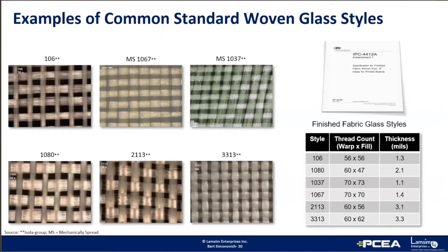MS glass, like 1067 and 1037, has the warp and the fill yarns mechanically spread to fill in the black resin-rich square areas. MS glass was primarily developed to improve laser drilling for microvias, and it has been adopted for high-speed PCBs to mitigate fiber weave effect skew, which I will discuss a bit later.